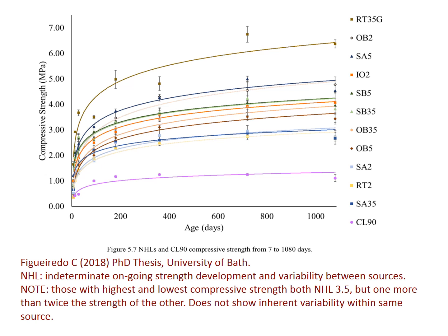A gain of half a MPa, which we're seeing steadily after about 6 months per year, will add up to a lot of gain. And of course, this equals densification and loss of effective porosity, even so far as they had that much effective porosity in the first place.